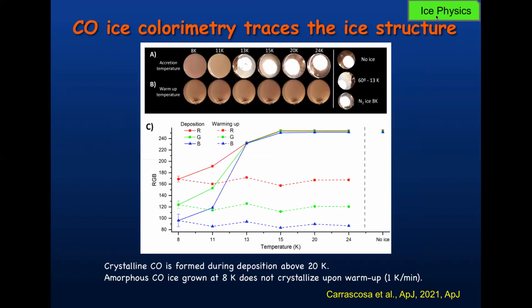And we have also done something new, which is colorimetry of the ice. In the case of CO, we observed that if you grow the ice at 8K and you warm it up, the color doesn't change. But if you grow it in a different experiment at 11, 13K, you see that the ice changes color. This white color is not related to the ice. This is the light at the back. So this is the real color, meaning that it becomes transparent because it crystallizes.